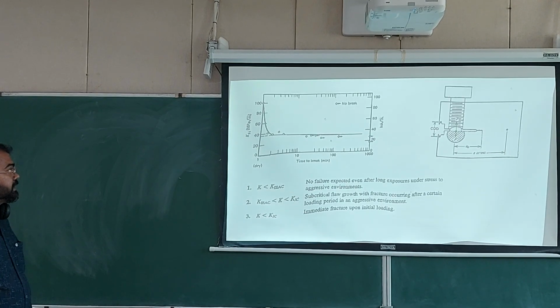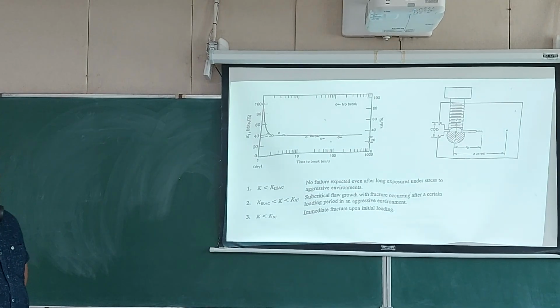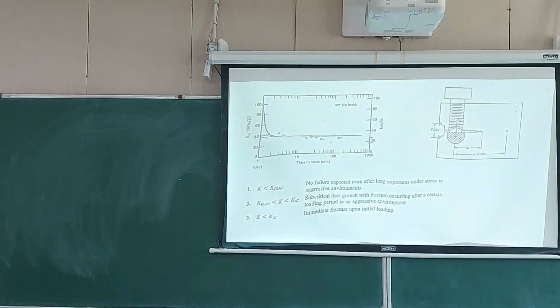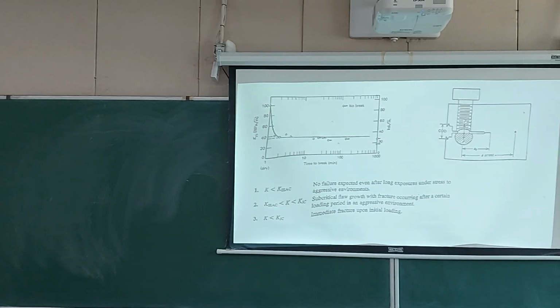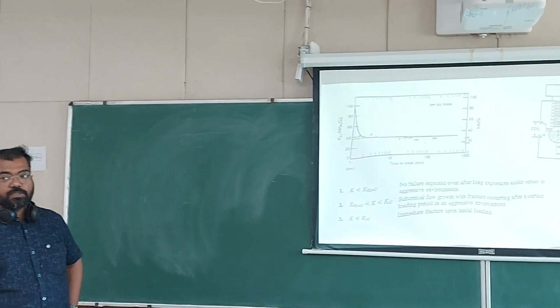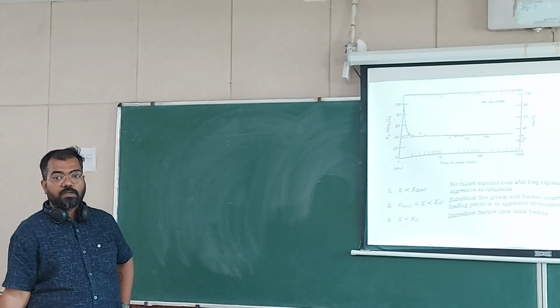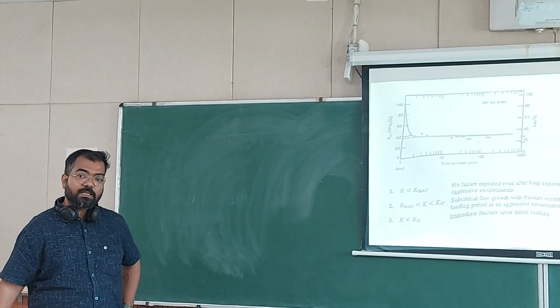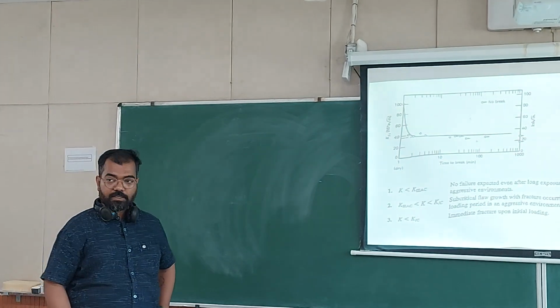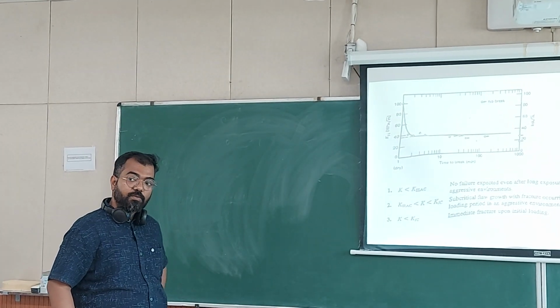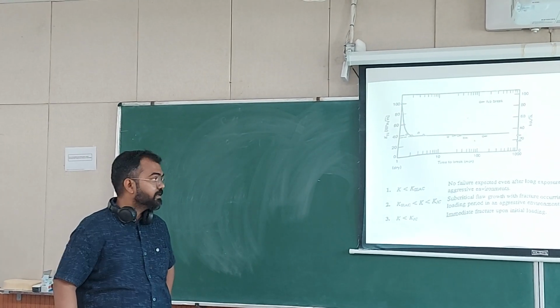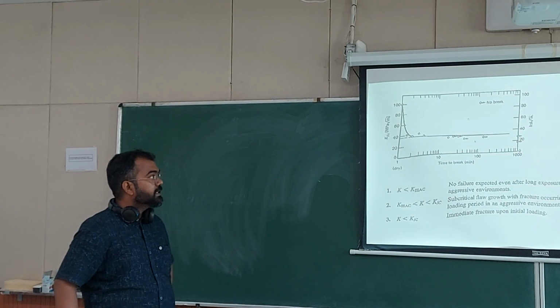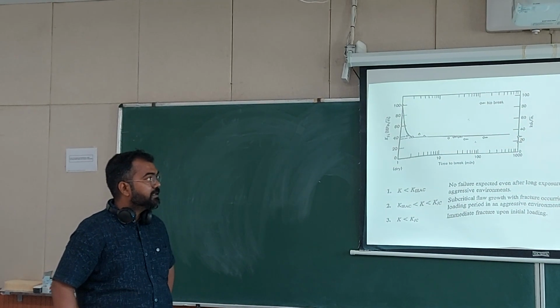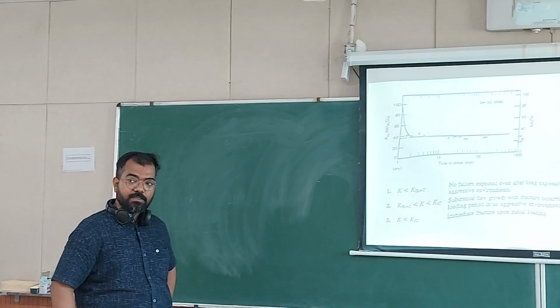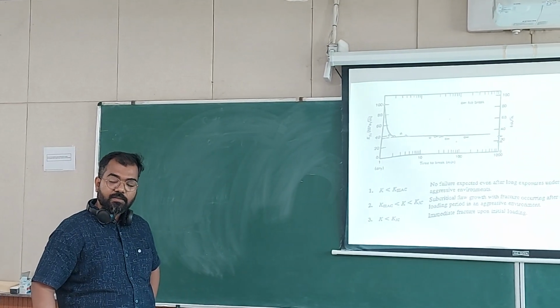So with increase in time, the fracture toughness appears to be decreasing, and there is a value below which, if you leave it for a very large amount of time, even then there will be no failure. So it is similar to what you saw in fatigue, endurance. And then we also discussed the modified CT specimen, and we have also seen a video of it.